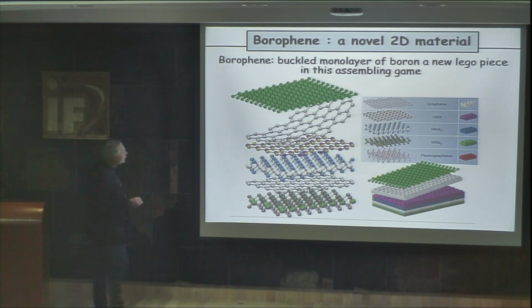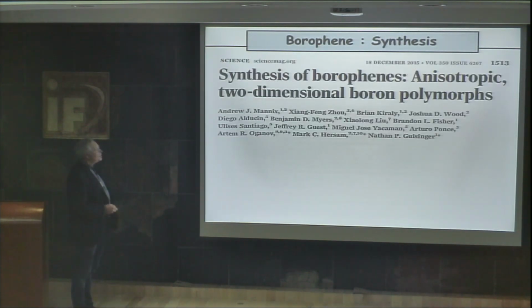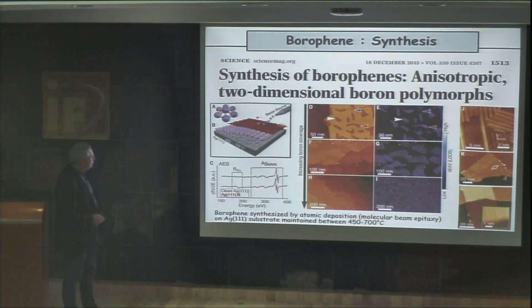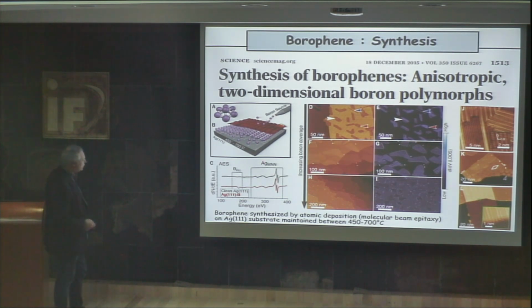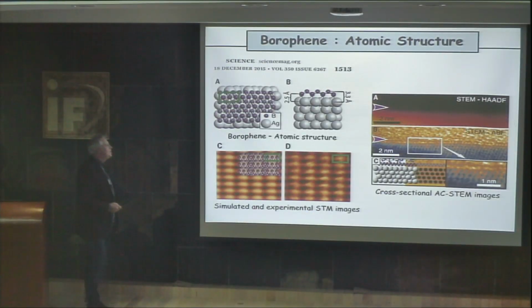And so the first example that I would like to present you is borophene. So borophene is a new type of 2D material that has been recently synthesized by the group of Mark Hersam in Northwestern University. And in fact, what they did is they synthesized borophene by atomic deposition, as you can see here. So it's molecular beam epitaxy, and this is performed at about between 450 and 700 Celsius on a silver substrate. And they observed the formation of a kind of flakes of boron, pure boron materials, and they investigated this using STM and also STEM.